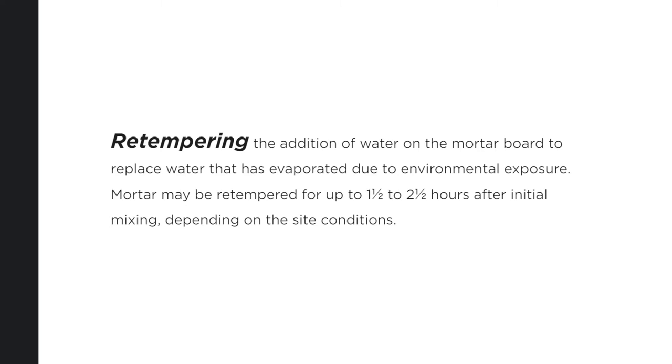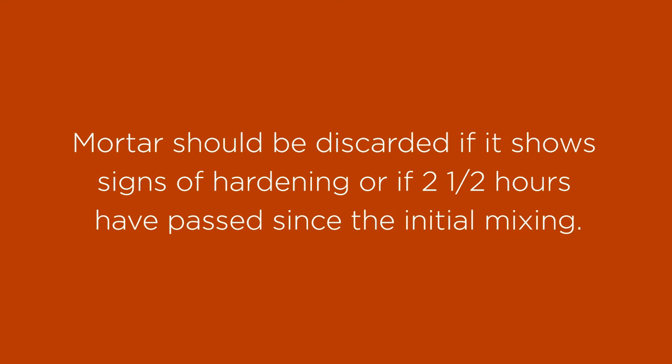Retempering is the addition of water on the mortarboard to replace water that is evaporated due to environmental exposure. Mortar may be retempered up to 1.5 to 2.5 hours after initial mixing, depending on the site conditions. Mortar should be discarded if it shows signs of hardening or if 2.5 hours have passed since the initial mixing.